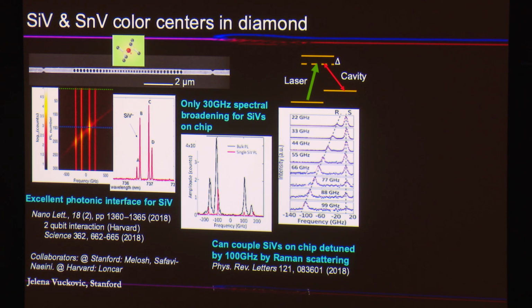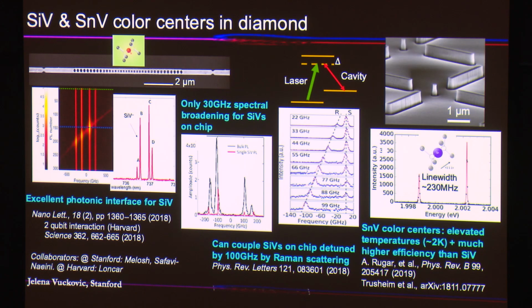And 100 gigahertz is much larger than the spectral broadening that we have between silicon vacancies, which means that maybe for smaller scale systems, you can just take separate lasers, drive different color centers with different lasers, detune them by the right amount, and always scatter resonant photons which you can interact at the output. So that's very promising, and this result was very promising for us because this was not something we could actually do with quantum dots, as an example.